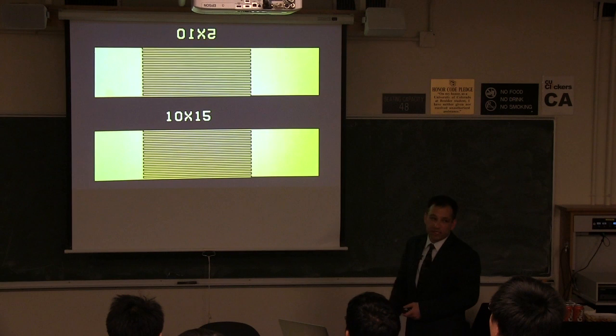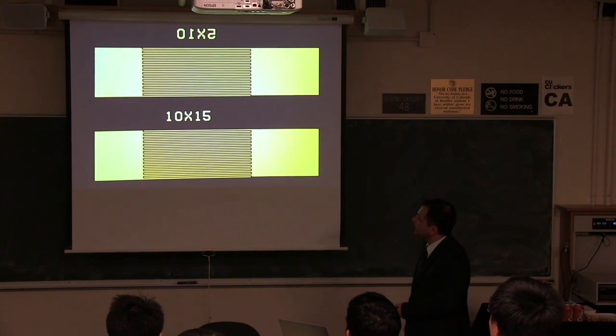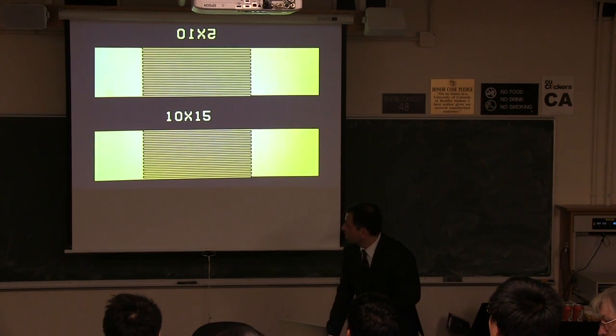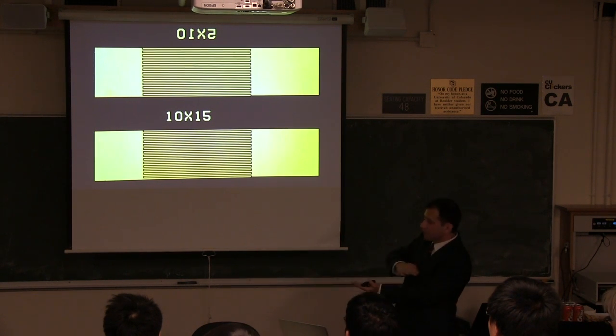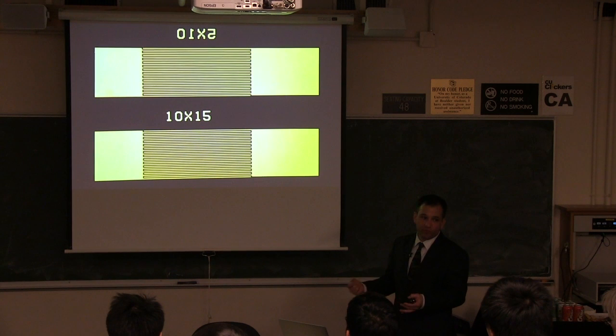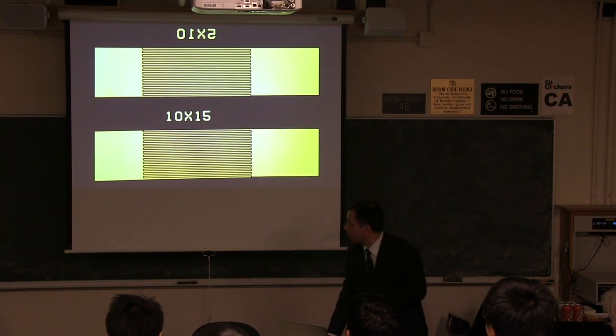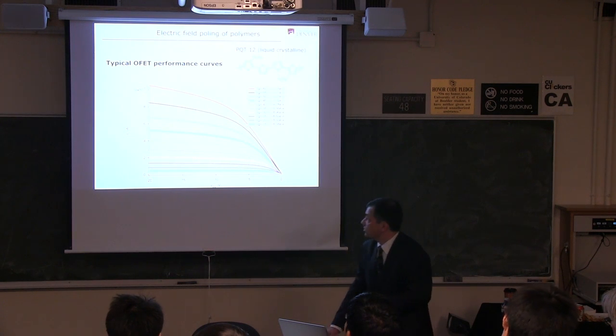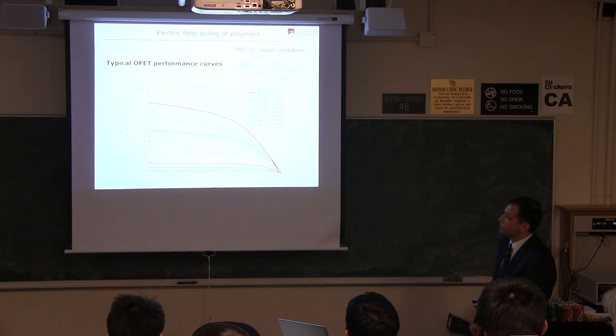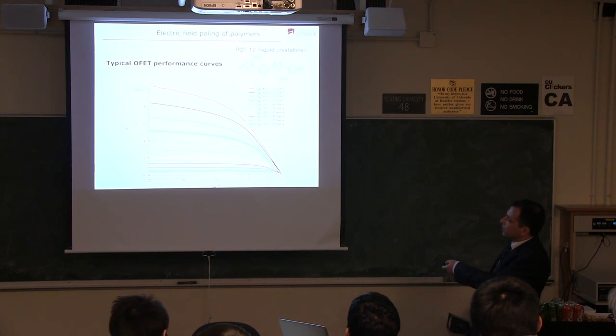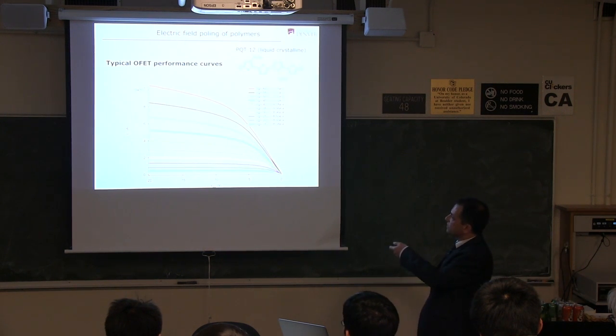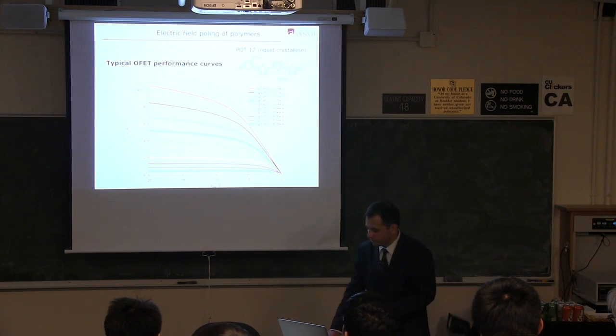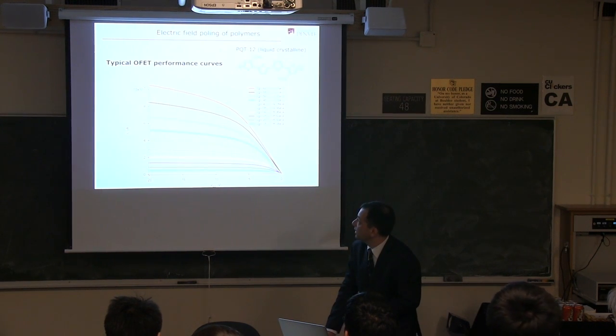This was an FET that was fabricated here in the CNL lab. You see these are IDEs with spacings of 10 to 15 microns, something like this, over a range of spacings. What Robert has done is deposit a wet film onto this material and apply an electric field as the film is forming, to align the molecules a little bit better. Here's a typical OFET performance we can get. We're still getting better at this, but we can get saturation at something like 10 volts VDS and gate voltages in the 10 to 20 range. Maybe you need to go up to 50 volts for some devices. So these are just typical performance curves for OFETs that we would make, and again, that was made and characterized right here.